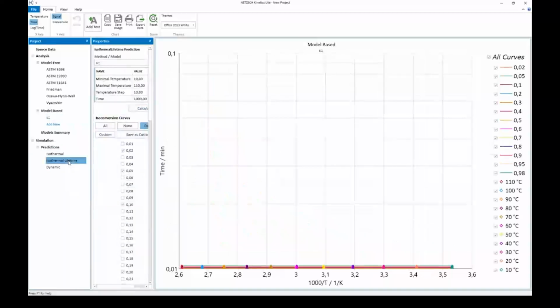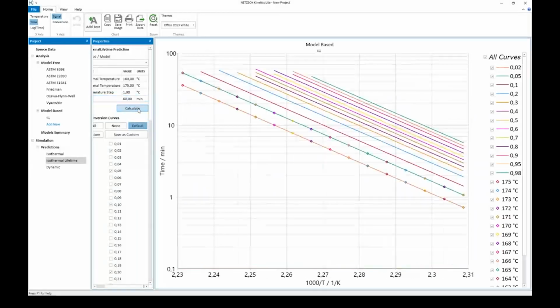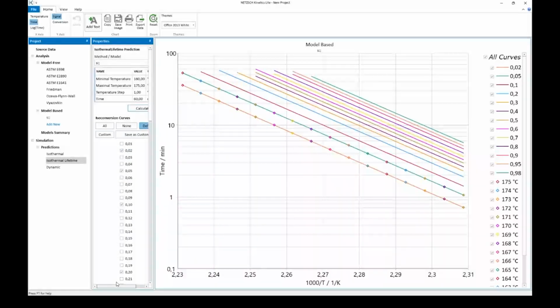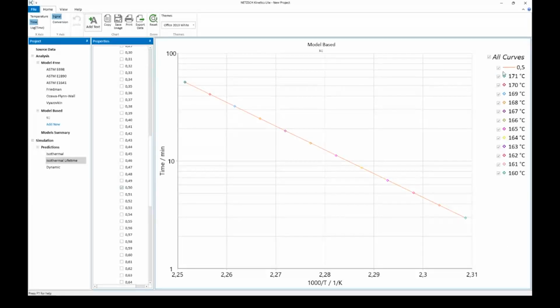We use isothermal lifetime. We will select between, for example, 160 and 175 degrees C with the step of 1, and it will be about 1 hour, 60 minutes. Calculate. We have something here, and now we will select only 50% of conversion. It is half of crystallization here. These are our results. We have only 50% of crystallization at different temperatures and a maximum at the last point is for 60 minutes, and it is this point, 171 degrees C. So we have 1 hour.